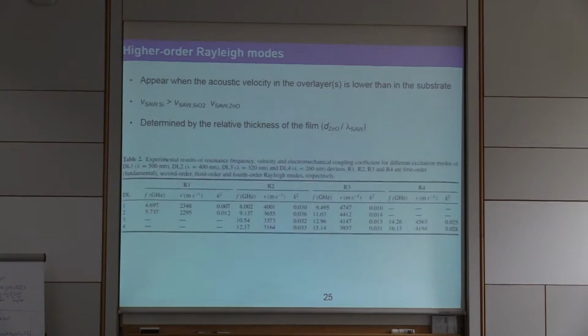Yeah? Okay. Good. Right. Okay, so a few more words on these higher order Rayleigh modes. They normally appear when the acoustic velocity in the overlay or overlayers is lower than in the substrate. So that's the case for us. Of course, already in the design that was taken into account, silicon has the largest surface acoustic wave velocity, larger than silicon oxide and also zinc oxide. And the exact resonance frequency is dependent on basically the ratio between the piezoelectric film and the surface acoustic wavelength. So it depends really on what design you use, where the Rayleigh modes come.